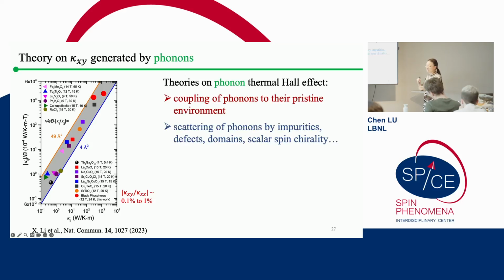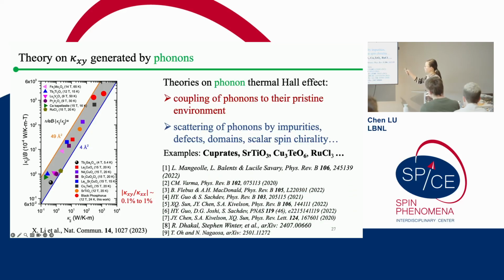But apart from that, there is a second type of phonon thermal Hall effect mechanism, which we call an extrinsic effect. This is related to the special scattering mechanism of phonons when they propagate through the material and carry heat at the same time. For example, what we call skew scattering of phonons induced by impurities, defects, structural domains, or scalar spin chirality, some special type of Skyrmion structure, can all give you a non-zero phonon thermal Hall effect from an extrinsic point of view. Here, I just list a non-complete list of some of the phonon thermal Hall effect theories that people proposed to explain the phonon thermal Hall effect in cuprates, strontium titanate, antiferromagnetic insulators, or even in ruthenium trichloride.